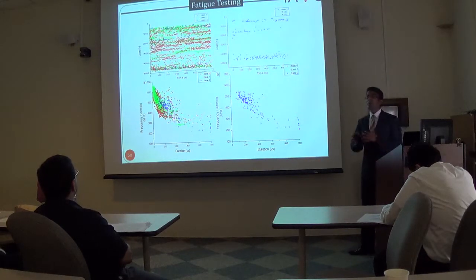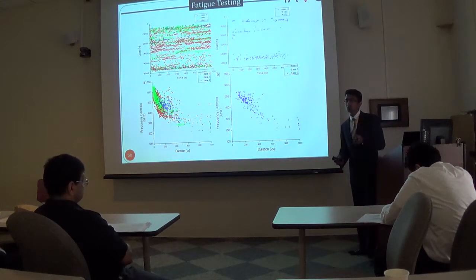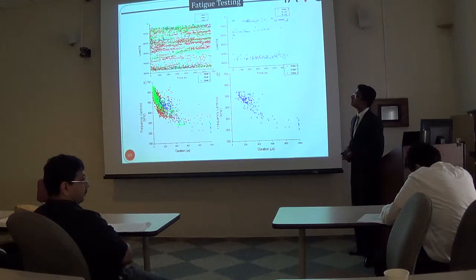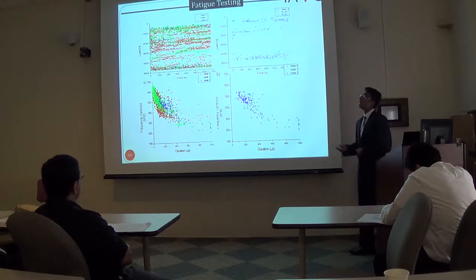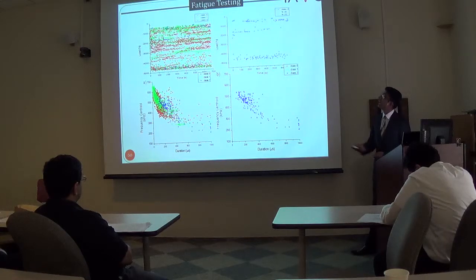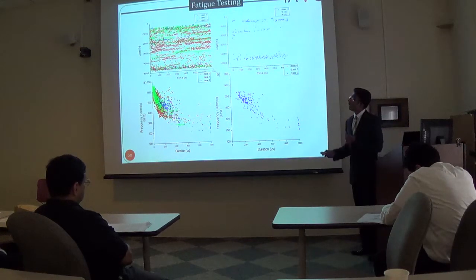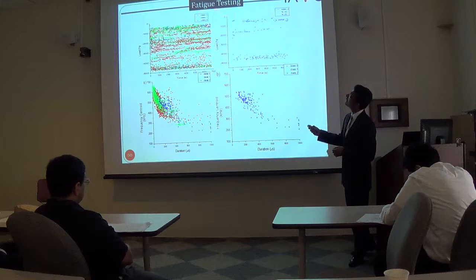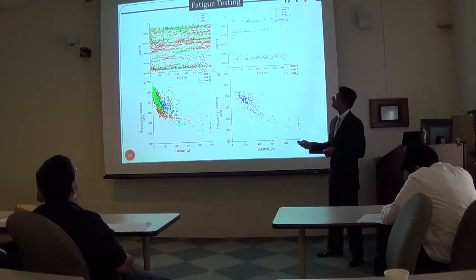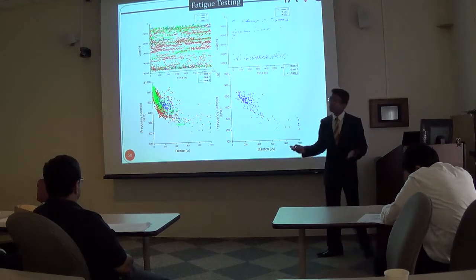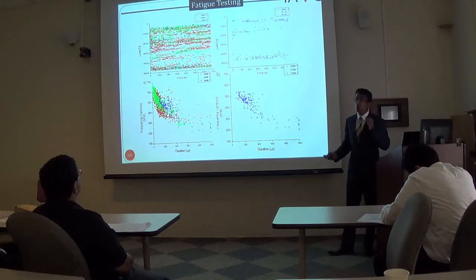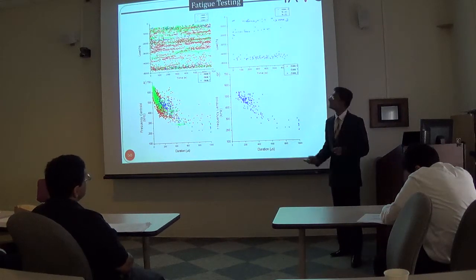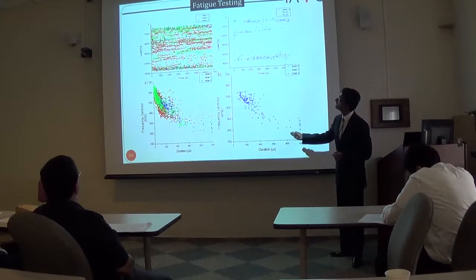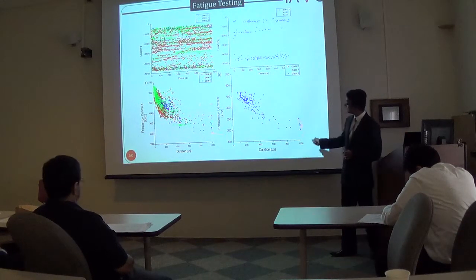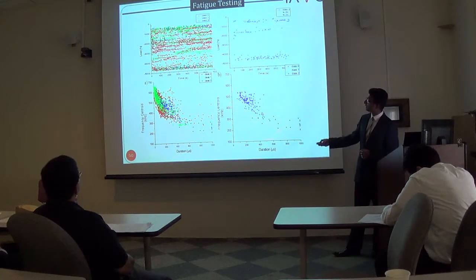So in order to now separate and potentially identify the source associated with the debonding in the fatigue testing of the composite stiffener component, pattern recognition analysis was performed and three main classes were identified. What can be seen here is that the class 0 and the class 1 signals, which are the red and the green, are pretty much active throughout the test. But the class 2 signal is seen to be active mostly during the loading profile of the test, as can be seen here. And further, these class 2 signals are seen to be associated with the low frequency centroid signals and high duration, as can be seen here.